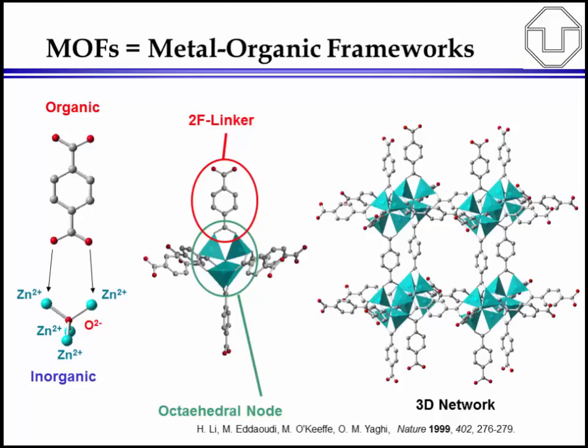And in this way, since this inorganic unit can connect to 6 of such linkers, it is possible to use the inorganic subunit as a node. So here, in this example, it is an octahedral node, so the organic linkers are pointing towards the corners of an octahedron. And this makes essentially the node concept, while the linker is typically a bifunctional or trifunctional linker, and can be used to extend and to link together the nodes into 3 dimensions.